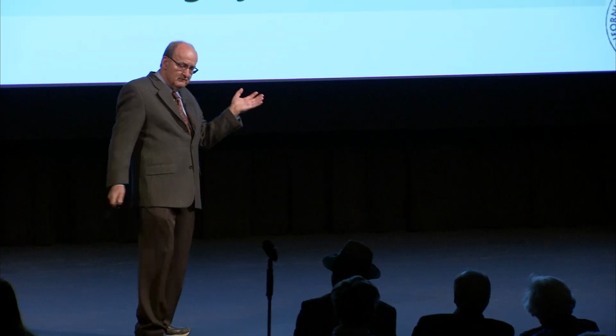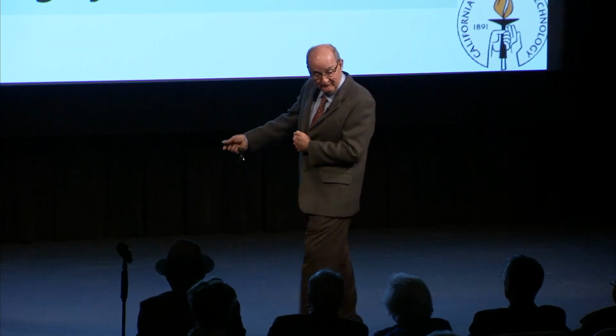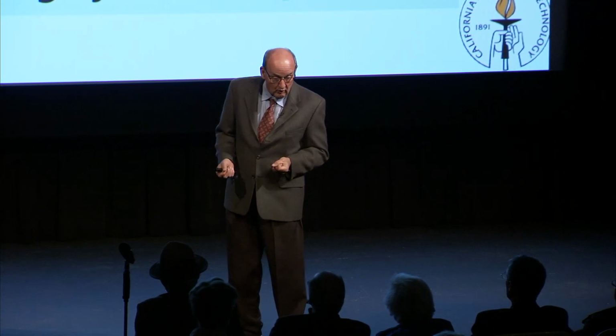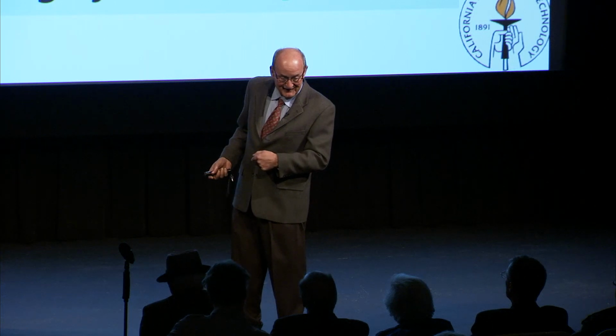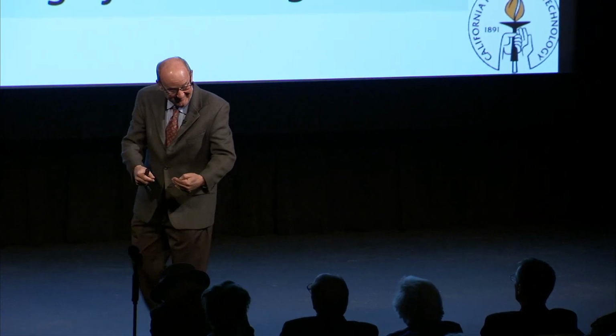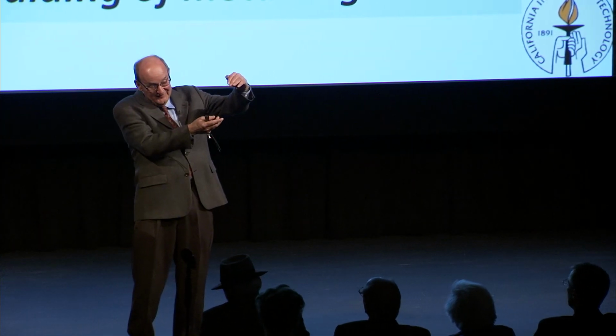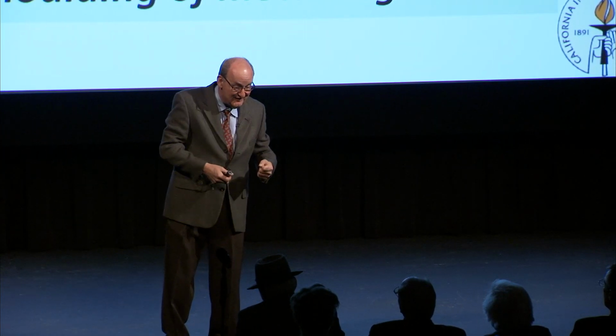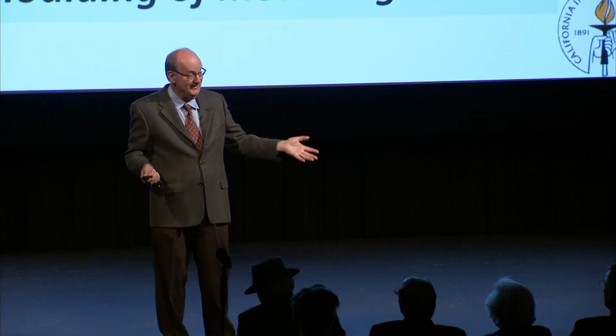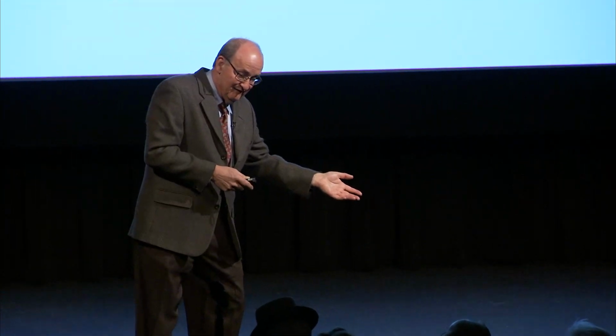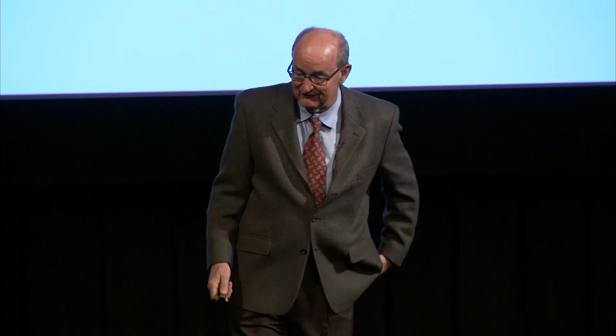Right? Well, here we have a metallic glass. Now, I told you what it has in common with plastic is it's a glass, and you saw it softens like a glass, and you can blow mold it, and technically you can injection mold it. What's the problem? That all sounds too good to be true. Well, it sort of is, because we run into the crystallization problem, and if we're molding it above the glass transition temperature but below the melting point, where it has the viscosity that plastic has when we injection mold it, well, if we hit crystallization, zoop, it's all over. Remember, it goes viral.